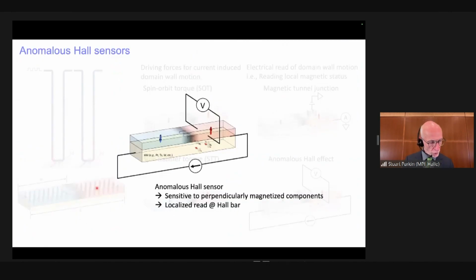So if there's just a few moments left, I want to briefly then say now recently we've gone beyond optical techniques to detect domain walls. And now we're using something called the anomalous Hall conductivity. What does this mean? This simply means, as shown in this cartoon, that if we have a magnetic material, when we pass current through that material, the current, the electrons, will be scattered from the magnetic moments and will be scattered preferentially to the left if the magnetization, let's say, is pointing up, or to the right if the magnetization is pointing down. And this leads to a transverse voltage, the Hall voltage.